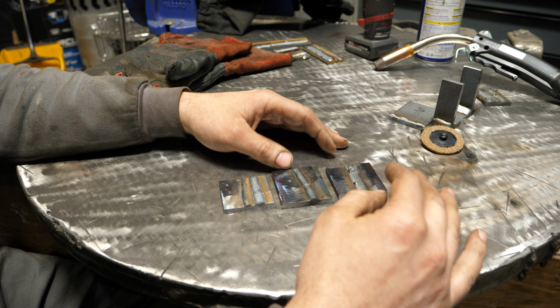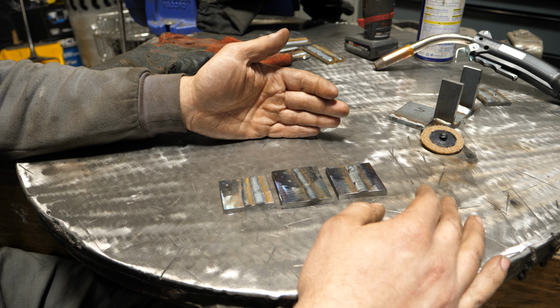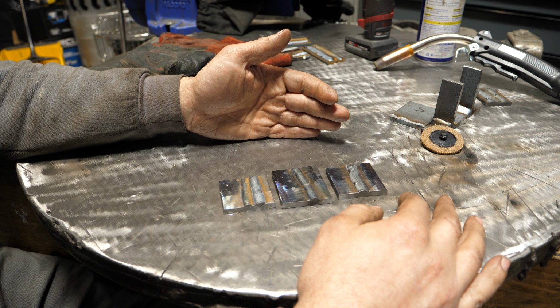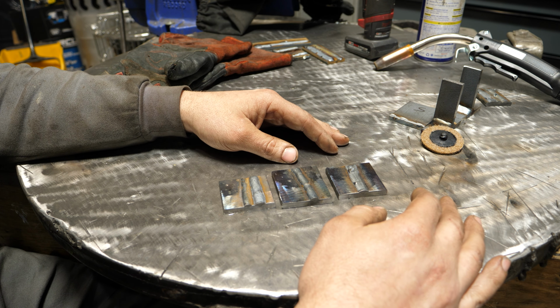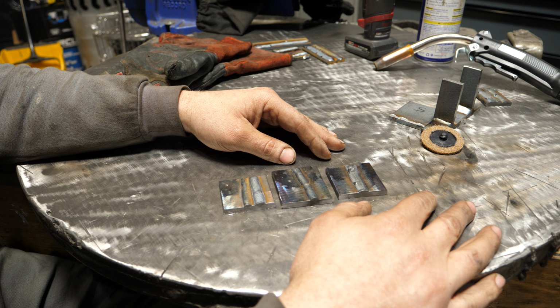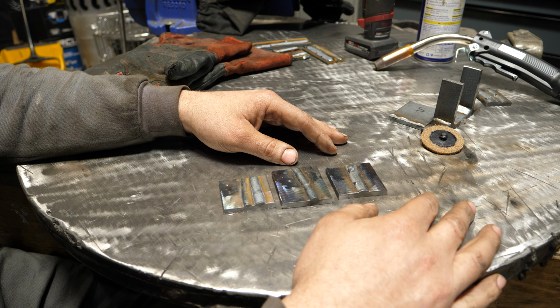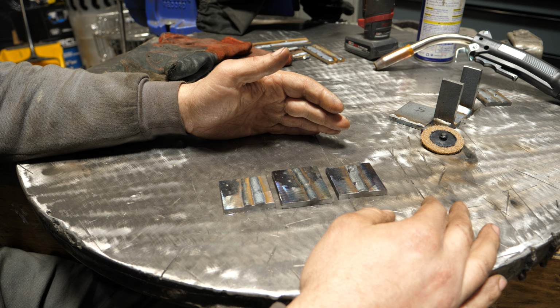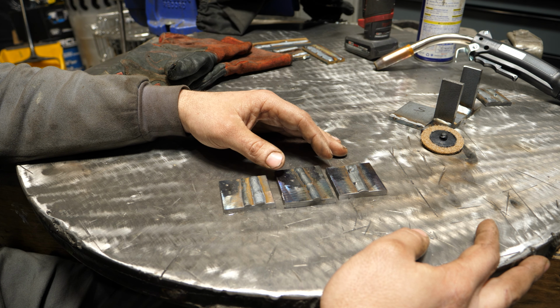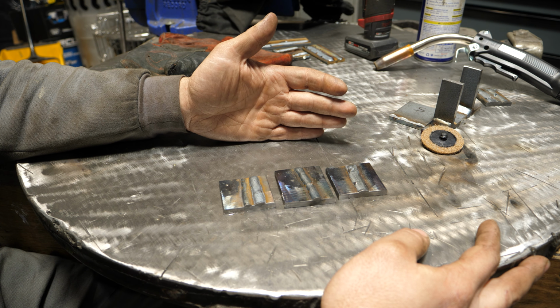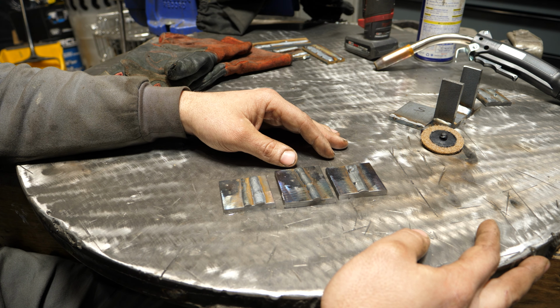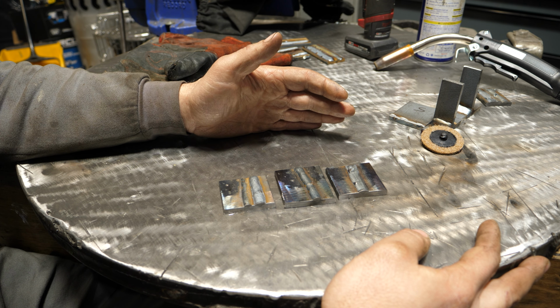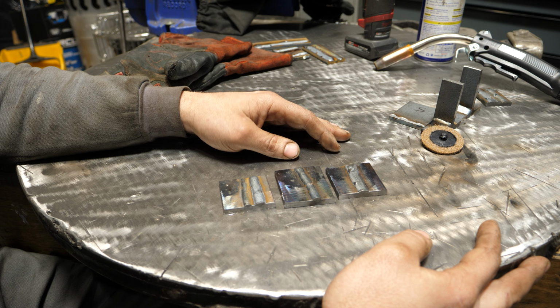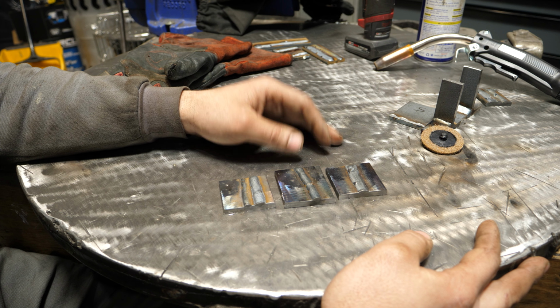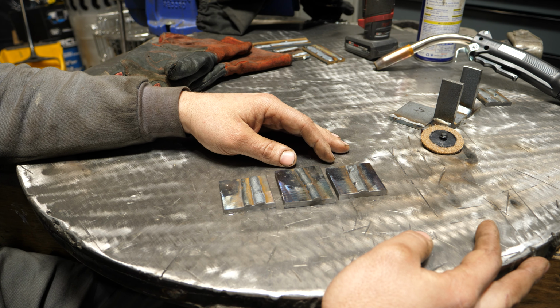Beyond that, it's, I guess, the travel speed being so high and the heat level being so significant. For most of you at home, how much quarter inch plus plate are you going to be welding where production value really matters? And how much are you welding that really needs really good root fusion and the strongest welds possible? Well, for a lot of you, it probably isn't too applicable. And that's why your standard short circuit MIG welders are so popular, because they're so versatile and easy to use and simple that they work for most jobs. But if you want to do some heavier steel, quarter inch and up, and a lot of it, the difference is night and day for production values and reliable root fusion when you go to spray.